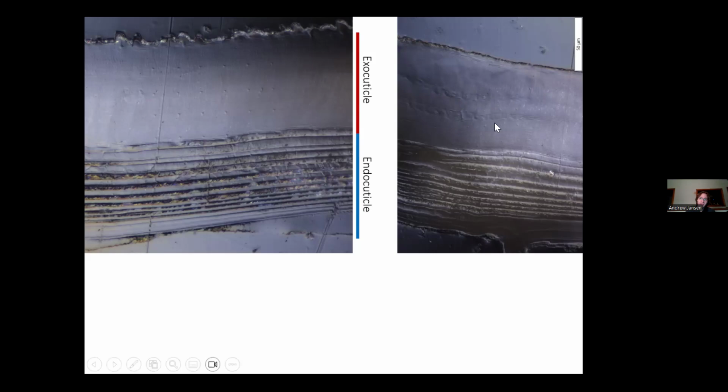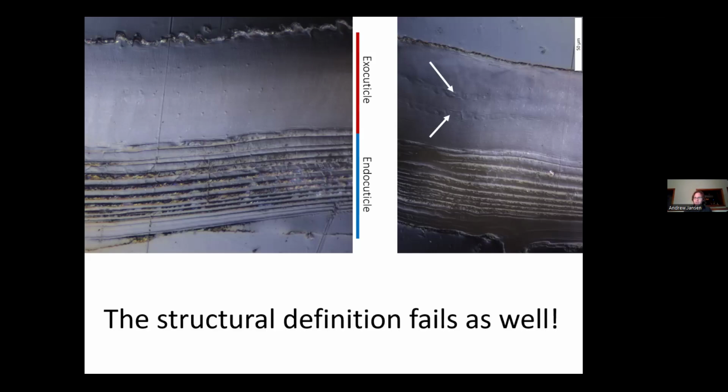But you can follow these layers and you can see that they are sandwiched within this material. You can see where these zones end, right? So it's an inclusion within the three-dimensional structure. So very clearly it's the same material, it just lacks the rotation that's happening in the adjacent domains. So these are unidirectional zones in the exocuticle, which is not really something that's well defined.